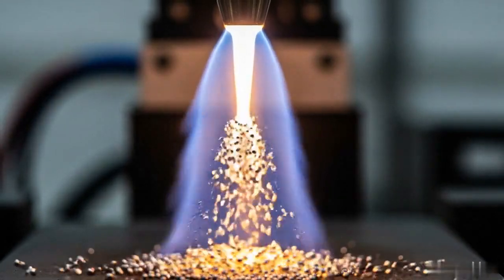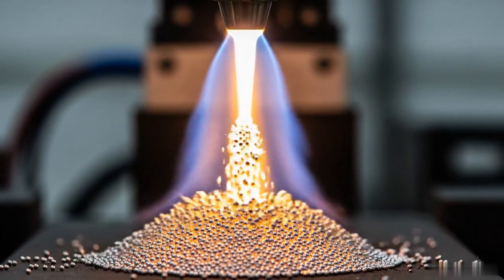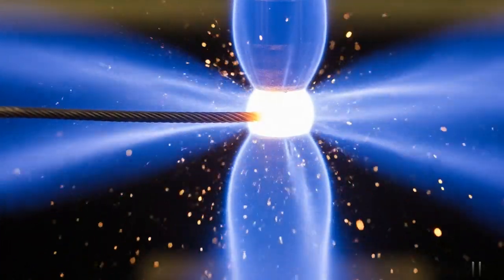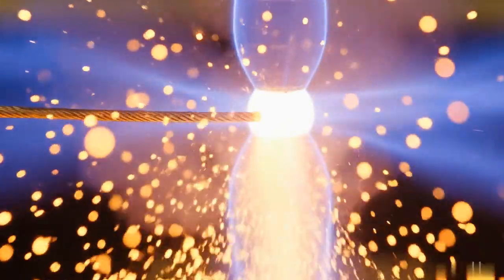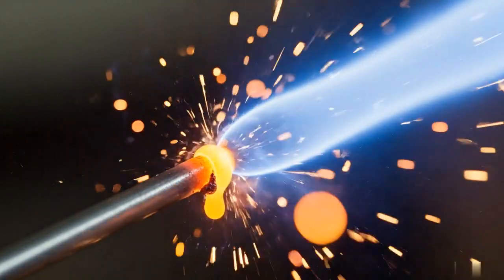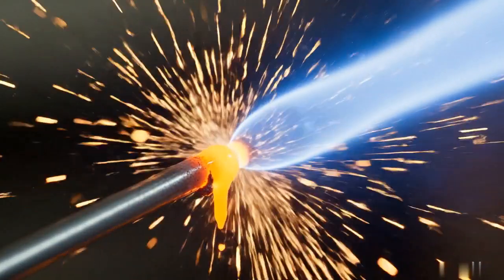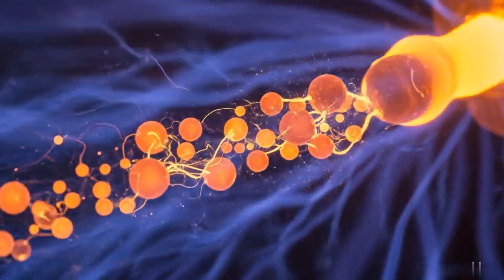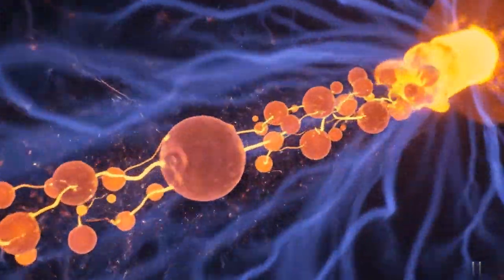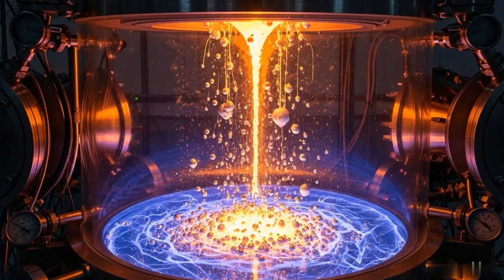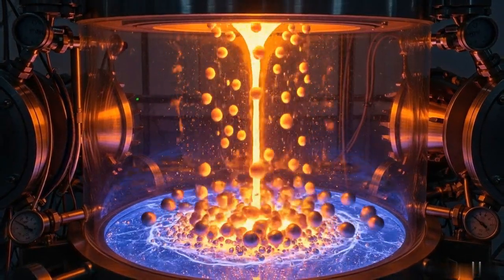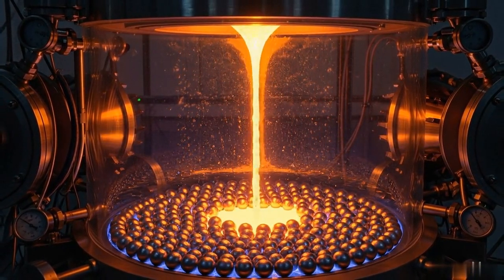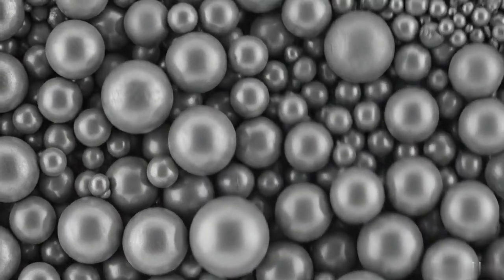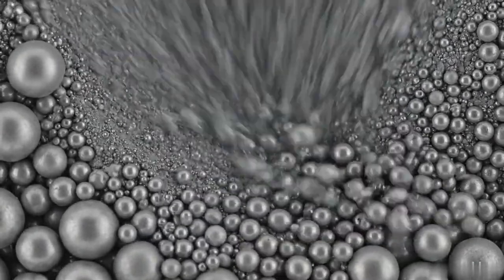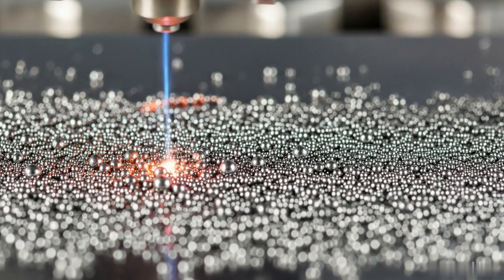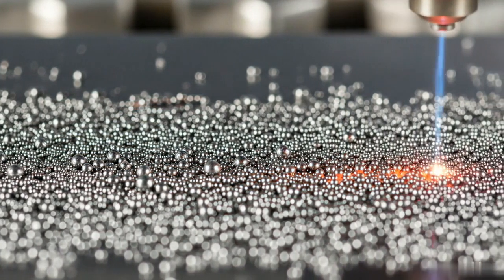Another major method is plasma atomization, widely used for high-quality spherical powder. In plasma atomization, a titanium wire or rod is fed into a high-energy plasma torch. The plasma, reaching temperatures over 10,000 degrees Celsius, melts the tip of the feedstock wire. Plasma atomized powder is highly spherical, with excellent flowability and low oxygen content. Typical particle sizes range from 15 to 150 microns, ideal for laser powder bed fusion.